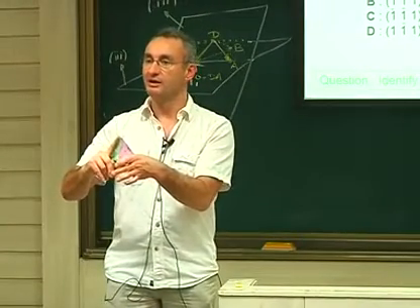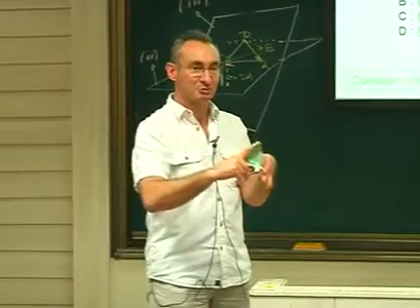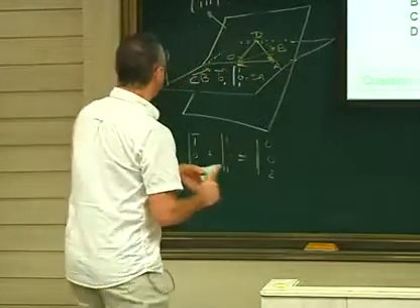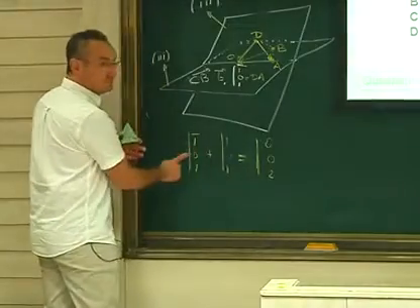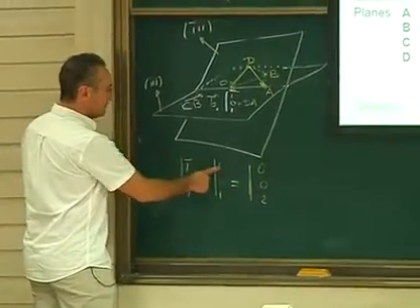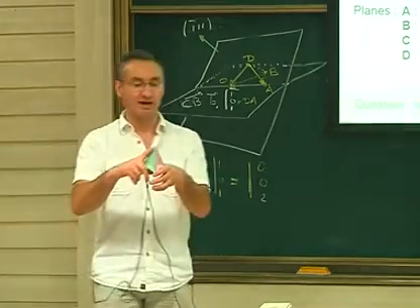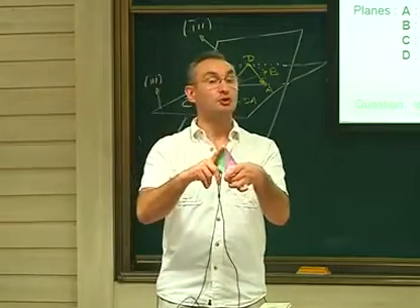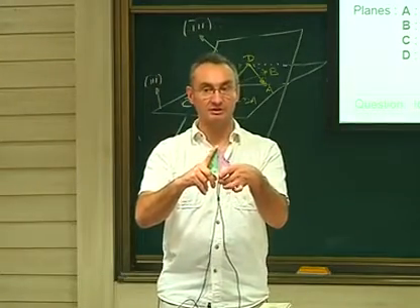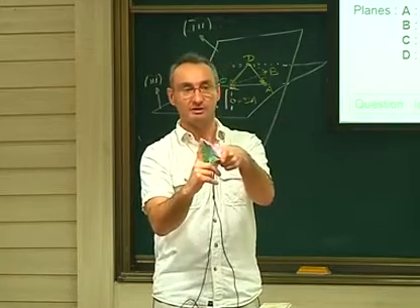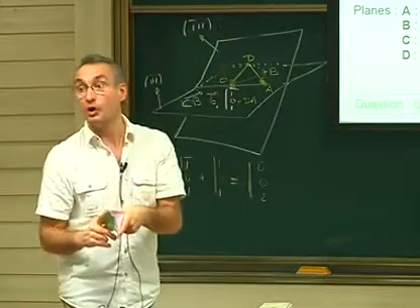They are not like those two typically, or those two here. I'd like to have this word. Somebody should say it. If you don't, I will say it: what is the dot product of the two? What is it? -1 plus 0 plus 1, 0. So they are orthogonal. Those vectors are perpendicular. And you can see it clearly in your 3D tetrahedron, they are perpendicular. So this interaction is called the orthogonal intersection.